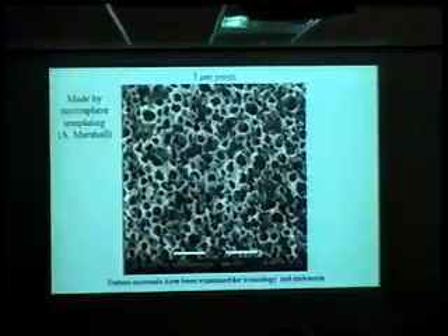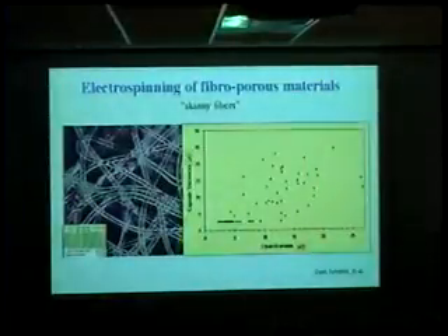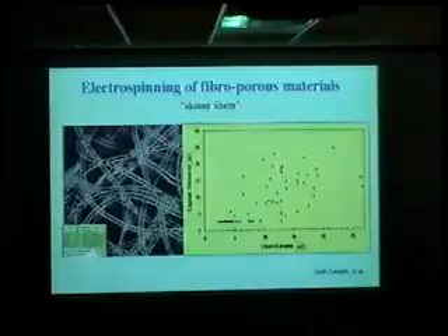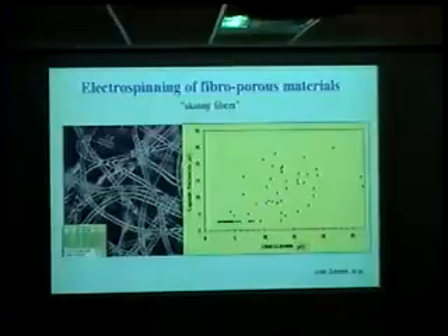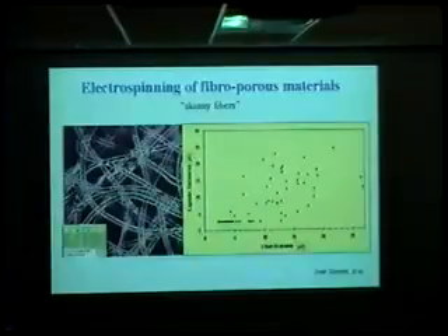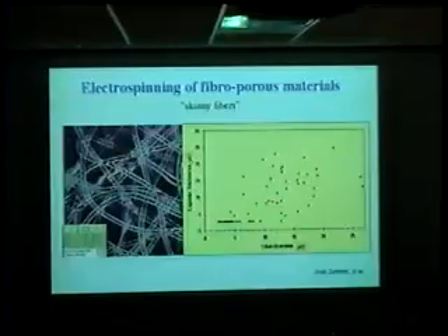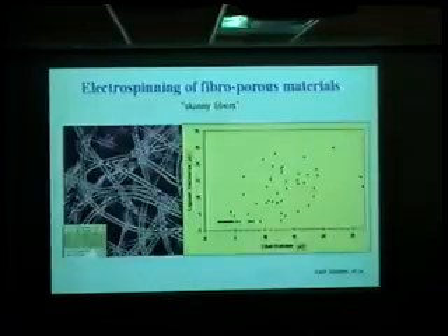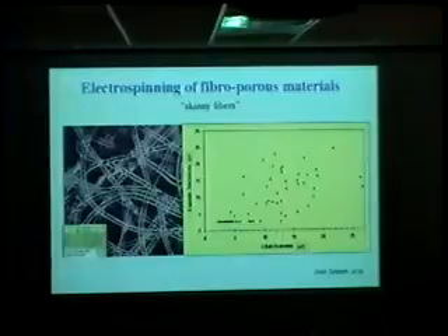interesting open structures. Another interesting experiment on healing that's coming out of our Engineering Research Center, Professor Joan Sanders and her group, is electrospinning fibers. And she's noticed that as the fiber diameter goes down to below 5 microns, this is the foreign body capsule thickness after a month of implantation, and the foreign body goes down to 0. The foreign body reaction goes down to 0 when the fiber gets below 5 microns. So, in fact, you might even say nanoscale fibers seem to be almost invisible to the body. And Joan is now making mats and materials of these fibers for implantation.